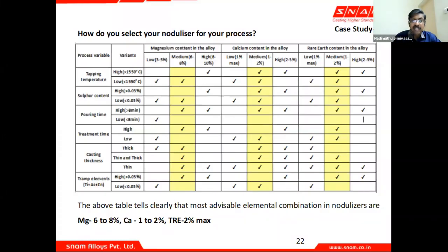I have higher sulfur in my charge mix. For some reason, my purchase says I will only get you this particular grade, or I have a pig iron which has only this percentage of sulfur, I am not able to get a lesser percentage. Fine. Then I have a pouring time, because for the same treatment ladle size, my boxes have different weights. So this particular product takes a longer time to pour, and therefore a longer pouring time. Therefore let me have a higher magnesium.